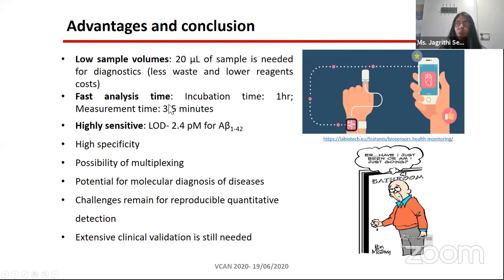So what are the advantages of this type of sensor is that we use really low sample volumes. Around 20 microliter of sample is needed for diagnostics. We have a really fast analysis time. The incubation time is approximately 1 hour, and measurement time is between 3 to 5 minutes. These are highly sensitive because we have been able to achieve 2.4 picomolar for A-beta-42. They're highly specific, and there is a possibility of multiplexing. If we can attach it to a proper microfluidic system, we can also do multiplexing.